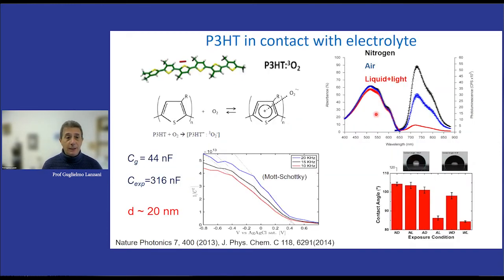The other thing I'd like to mention here is, again, the interface. The interface has been evaluated, for instance, measuring the Mott-Schottky plot. It's on the order of 20 nanometers. So that means we're not talking about a flat 2D surface as the interface. Here we are talking about an interpenetrating region in which the polymer, the water, the protein, and the ions are mixed together. So there are about 20 nanometers in which the polymer is swelling and the water is going in, and so the dielectric function is changing. Oxygen is making a complex with the polymer, becoming a trap for the negative charge, and a strongly charge-transfer state is formed in the polymer due to oxygen penetration.